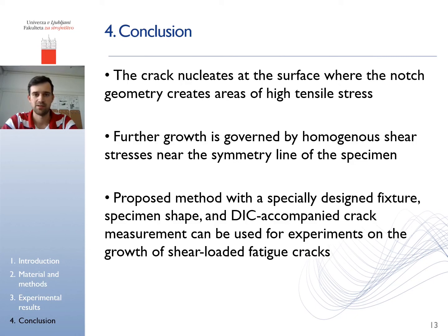We concluded that the crack nucleates at the surface where the notch geometry creates areas of heightened tensile stress, as we predicted during notch analysis. Further growth is governed by homogeneous shear stresses near the symmetry line of the specimen. The main conclusion is that the proposed method with a specially designed fixture, specially designed specimen shape, and DIC-accompanied crack measurement can be used for experiments on the growth of shear-loaded fatigue cracks.